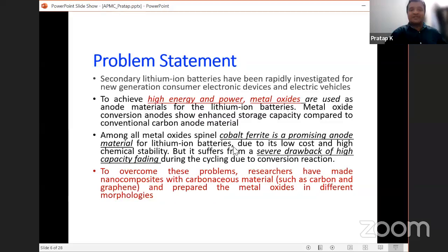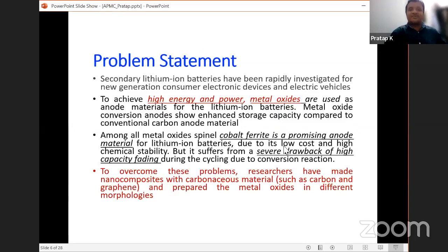Among these metal oxides, cobalt ferrite is a promising anode material for lithium ion batteries. Why? Because it has high chemical stability and comparatively low cost. When we identified the advantages of this material, we felt we should also know its drawbacks. The drawback of this material is high capacity fading. High capacity fading, you all know what it means. When you buy a mobile phone and charge it completely, the charge will last for 2 days.